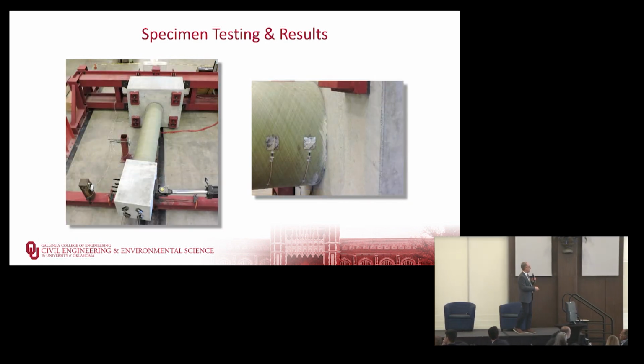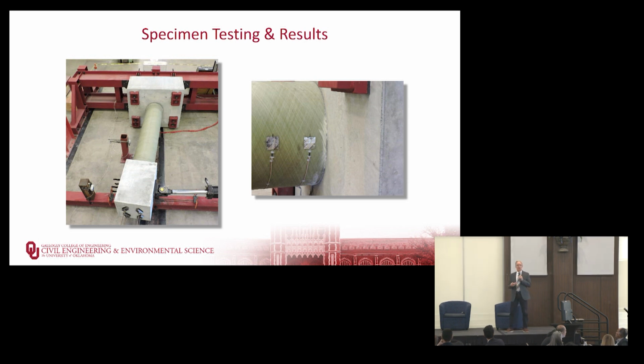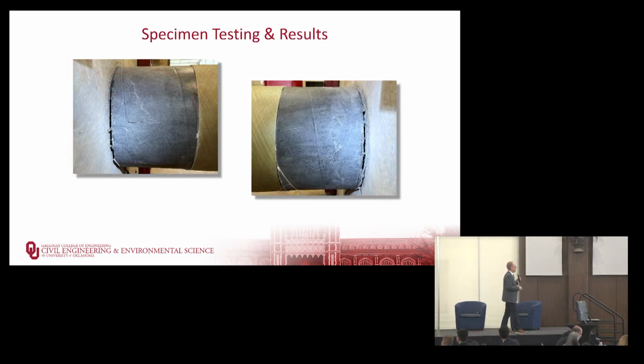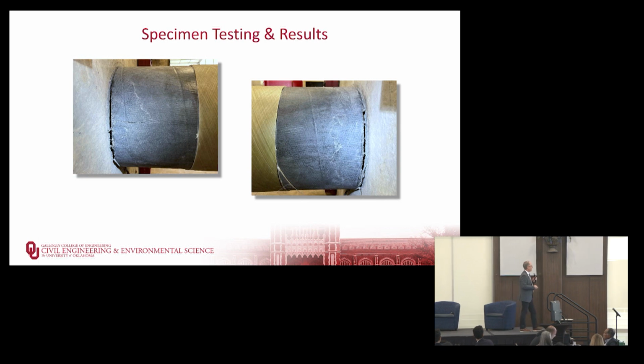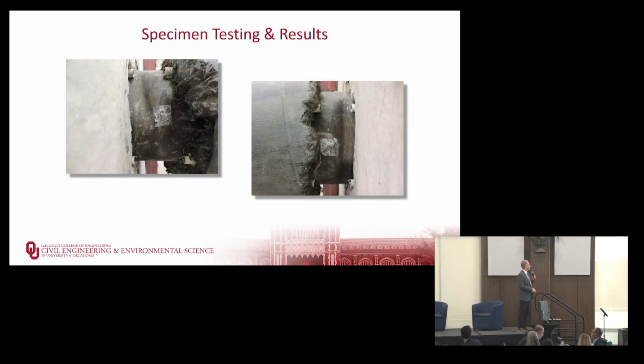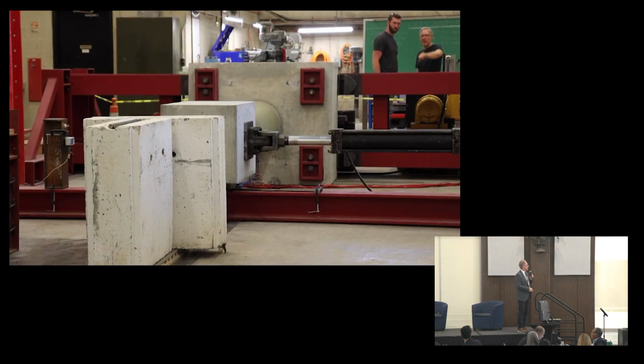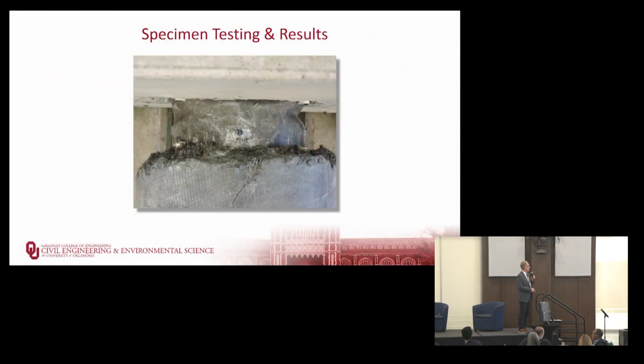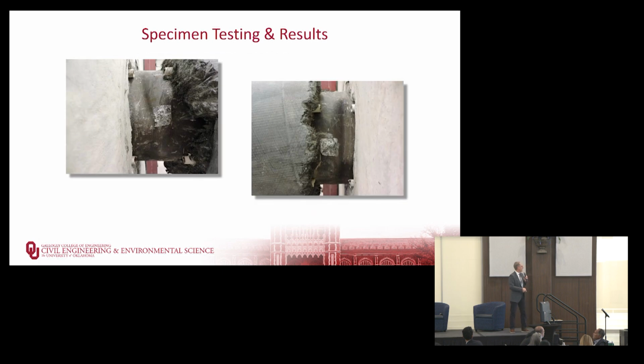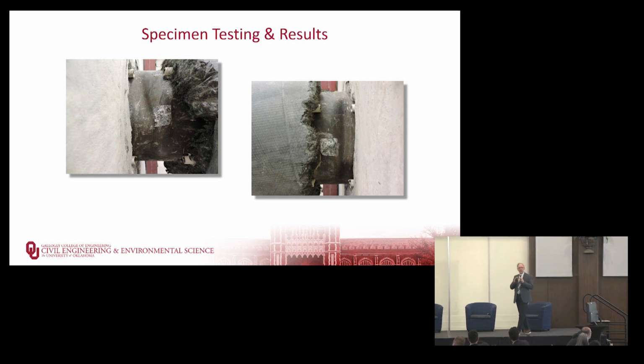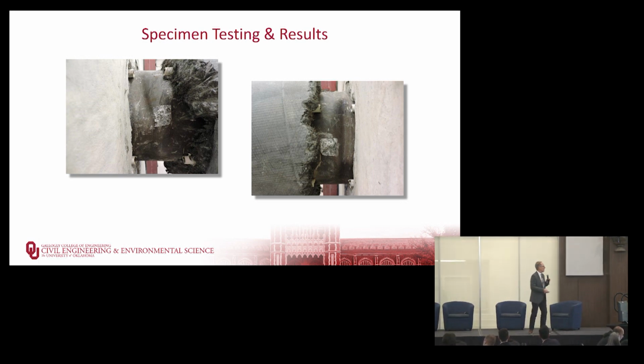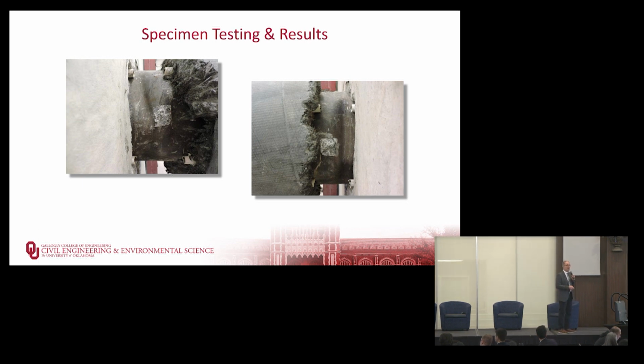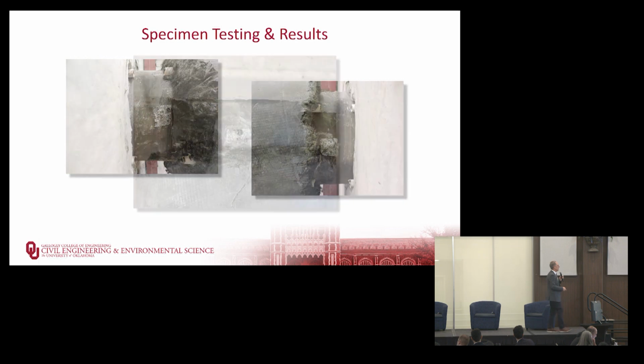And then this is one with the UHPC core. You can see near failure, there's not as much failure of the FRP because the UHPC is providing a lot of confinement because of the steel fibers inside of it. Then we opened up, it looks in really, really good condition. There were still some fractures, some cracking, and then removing the FRP, the UHPC, you can see the fracture. So you can see the steel tube. With the UHPC, the steel tube buckled in a much more three-dimensional way because of the extra confinement of the UHPC, which increased its apparent strength. And we did not fracture the steel tube for the UHPC column, and we tested 2 identical specimens for each of them. And then looking down.